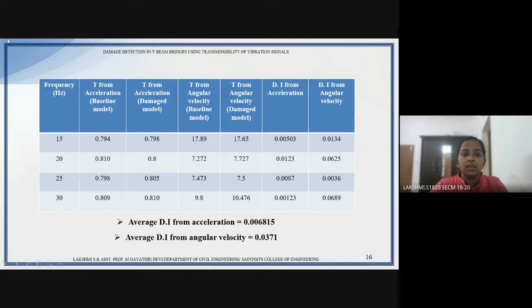So the corresponding transmissibility value based on acceleration, that is the ratio of acceleration from node 1 to node 2 at these particular frequencies, was calculated. Similarly, angular velocity was also used for calculating the transmissibility value. Then, based on the transmissibility obtained, damage index from acceleration and damage index from angular velocity was calculated using the equation that was mentioned before in the slide. So we were able to come to a result that the average damage index was 0.006815 from acceleration, and that from angular velocity was 0.0371.